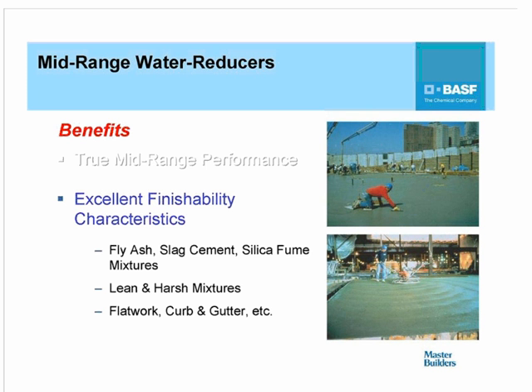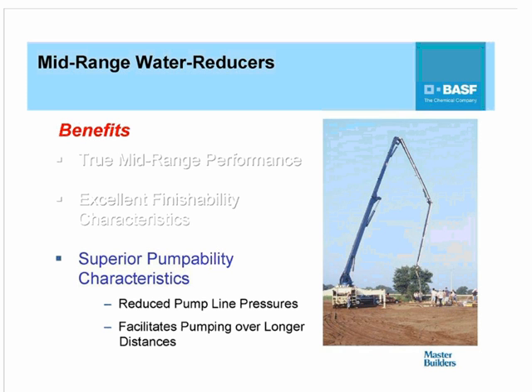Now, the benefits of these mid-range water-reducing admixtures basically lie in the excellent finishability that they provide, especially in lean and harsh mixes, working with supplementary cementitious materials. Mixes that tend to be sticky can benefit from the use of most mid-range water-reducing admixtures. Typical applications for these materials include flat work, curb and gutter, and so on. One of the other benefits of mid-range water-reducing admixtures is the fact that they provide superior pumping characteristics when used in concrete, which results in reduced pump line pressures and also the ability to pump over longer distances because of the effect that they have in reducing pump line pressures.